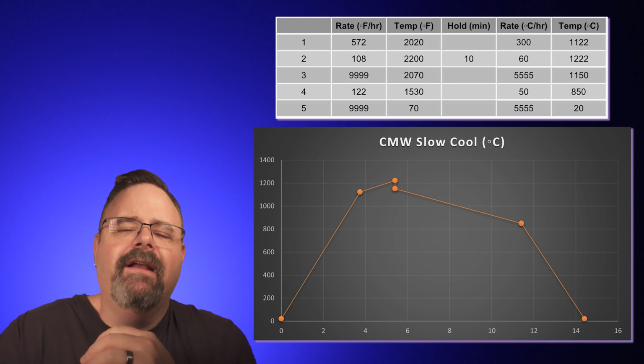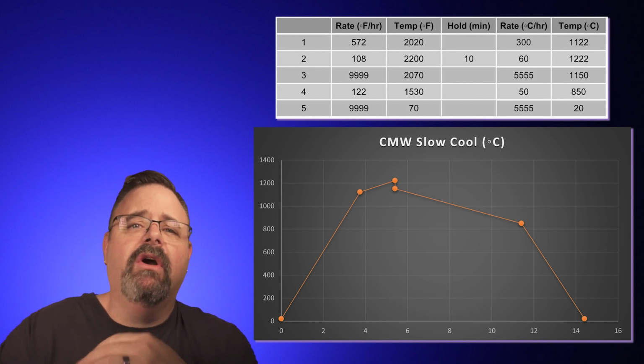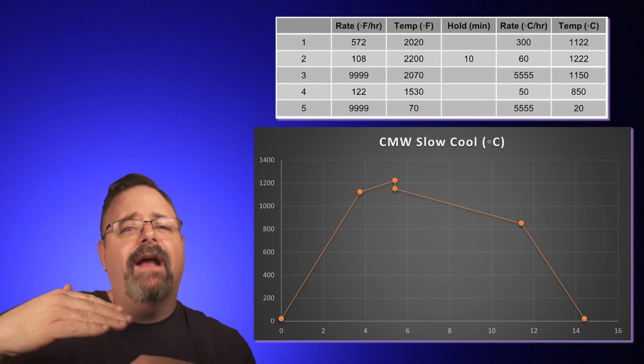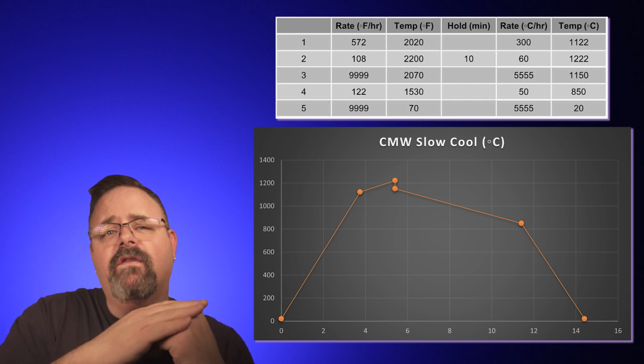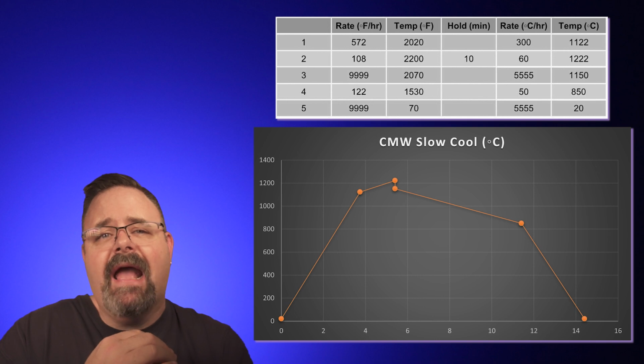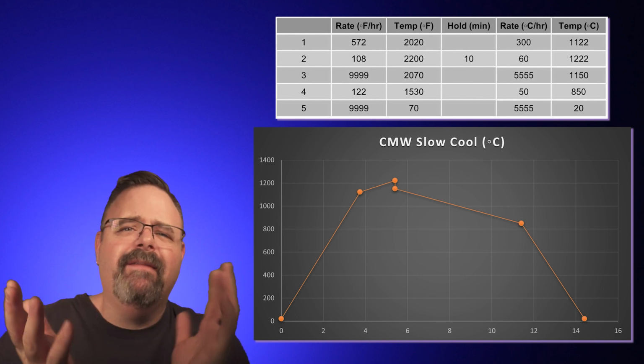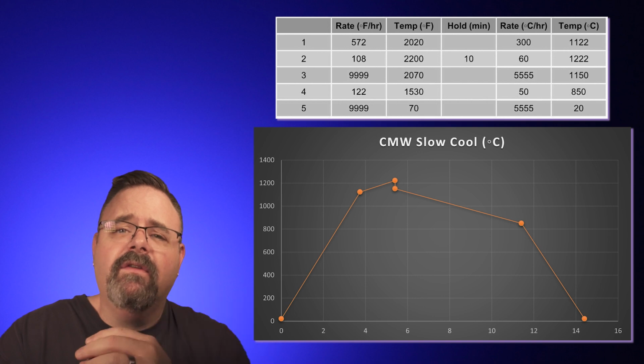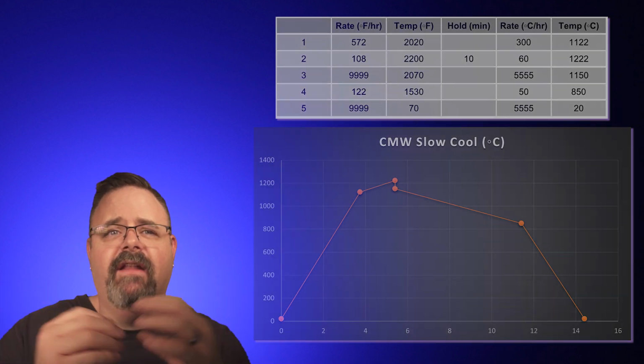Now, there are a million slow cool firing cycles out there, and you can use any of them. They're all basically the same thing. Some of them will pause here and hold there and, whatever. This is my basic slow cool firing cycle. It's the same concept as the crystalline cycle. You go up to your peak temperature, allow the kiln to crash down to about 1150 C, and then you slowly go down. I go at 50 degrees C per hour, down to about 850 C. It takes about 6 hours for the cooling cycle, and that's how I got those crystals in that glaze, by just giving the chance for crystals to grow throughout that firing. You can do whatever you want with them, but that'll get you a good level of crystal growth with that crystalline glaze.